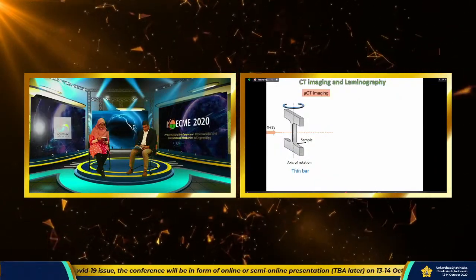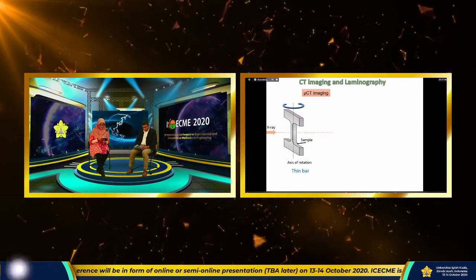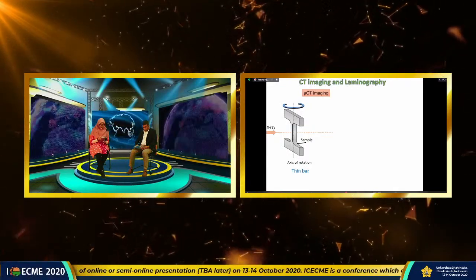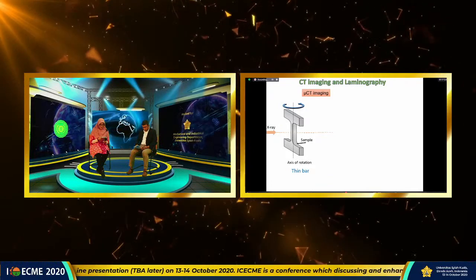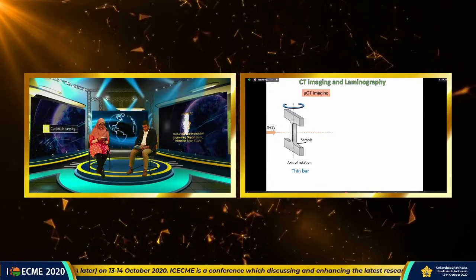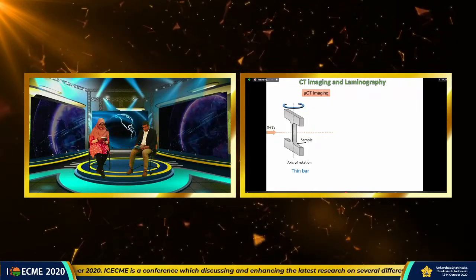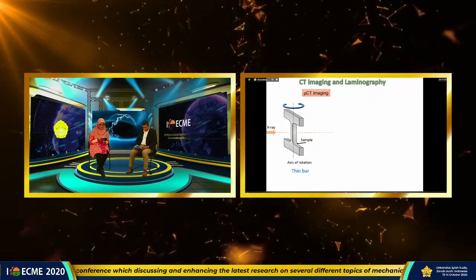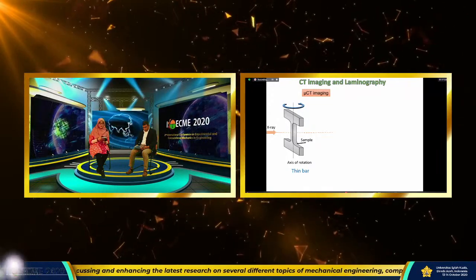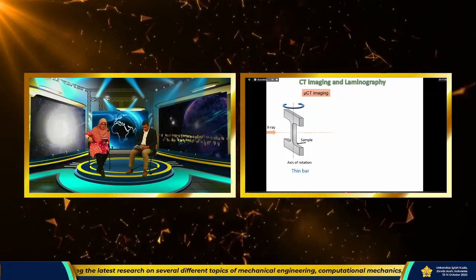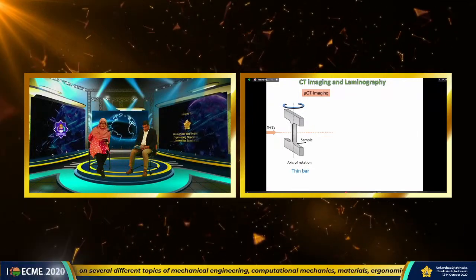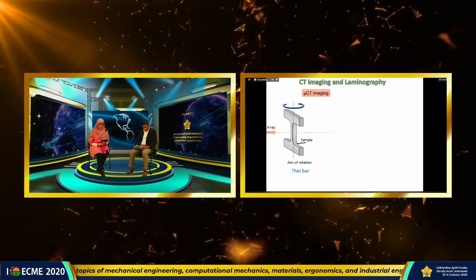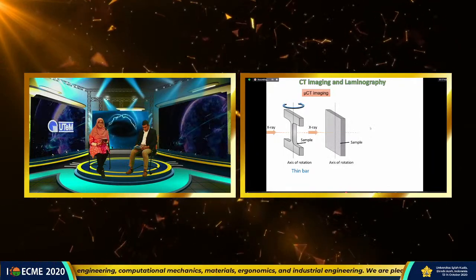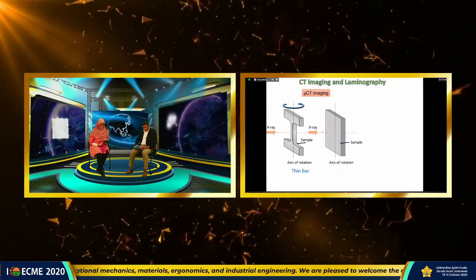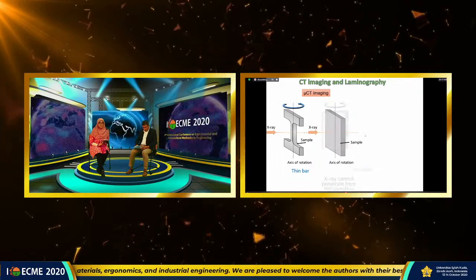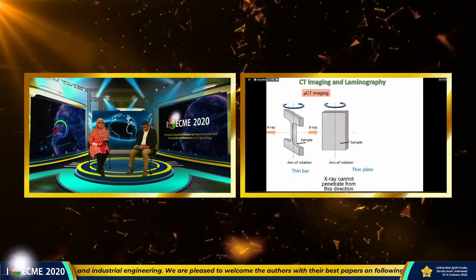Next, I'm going to explain the difference between CT imaging and laminography. For CT imaging, you have to rotate the sample to obtain a 3D image. Then the penetration thickness of the X-ray must be small enough for all directions. It means that only a thin bar can be imaged. In the case of a plate like this, X-rays can penetrate this direction, but cannot penetrate from this direction.